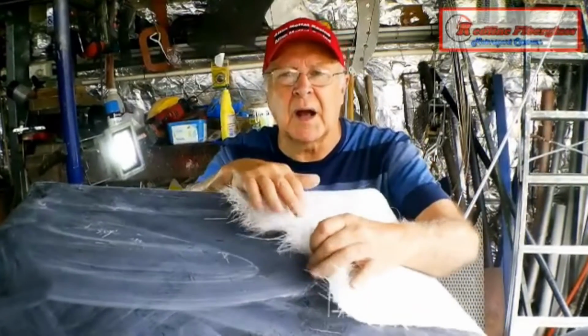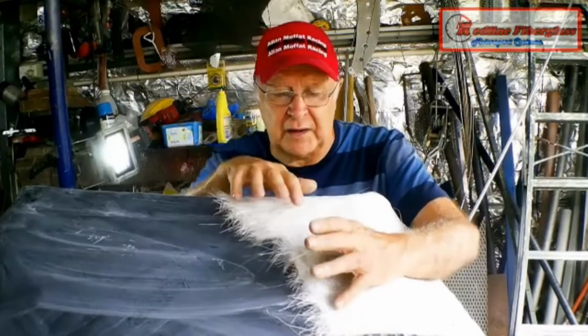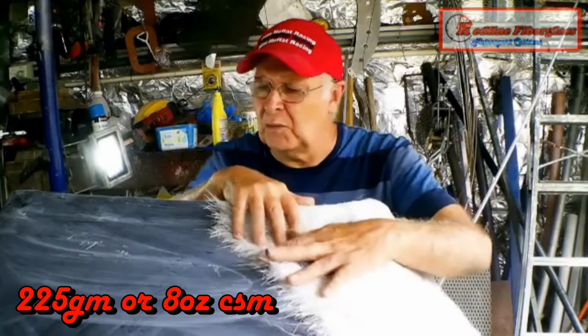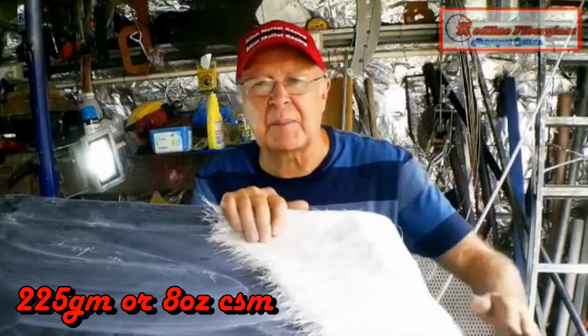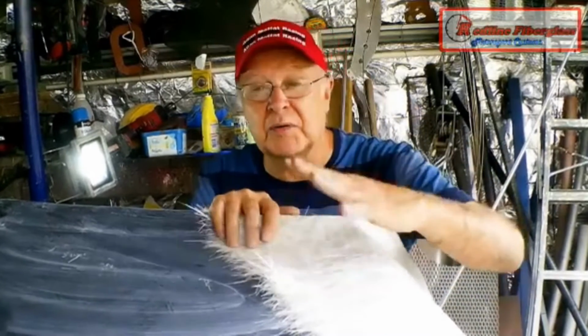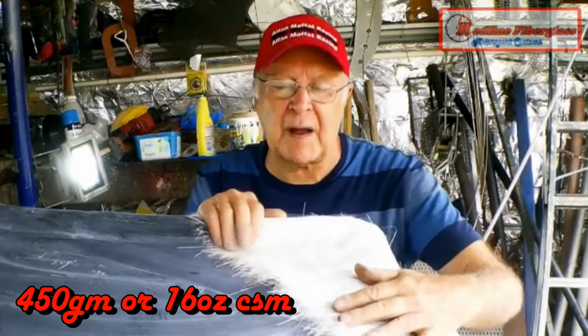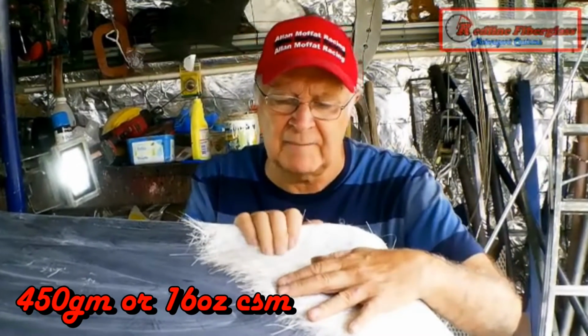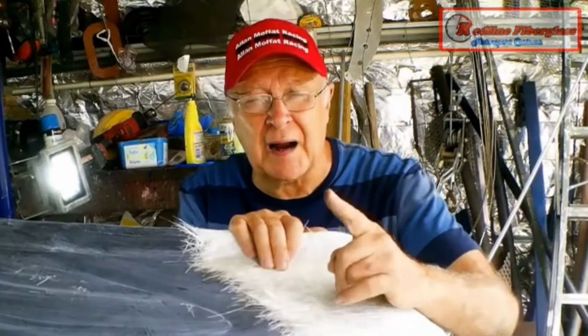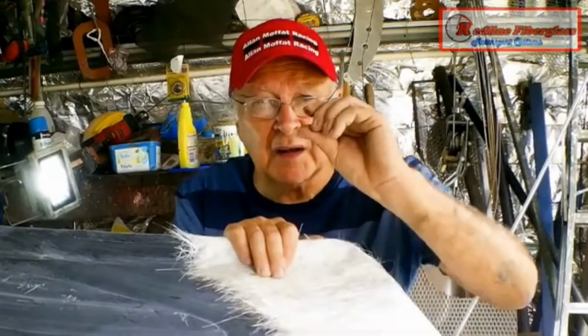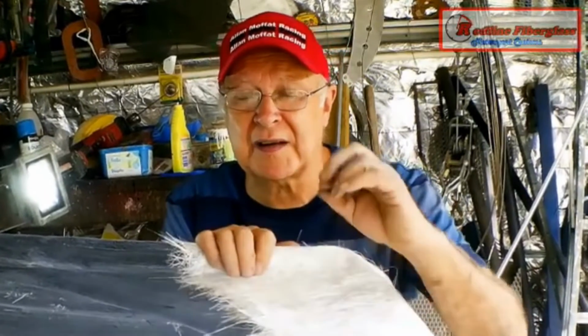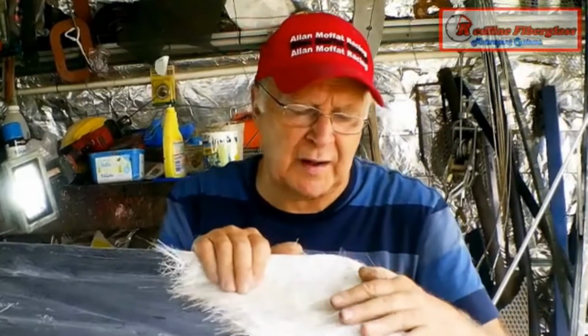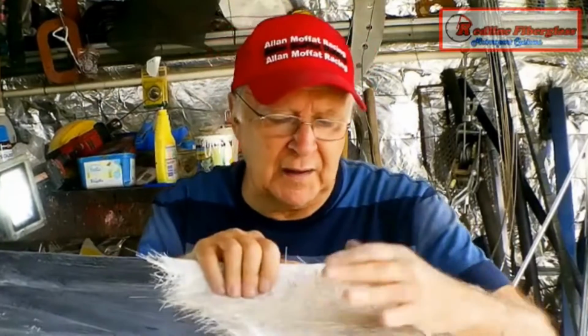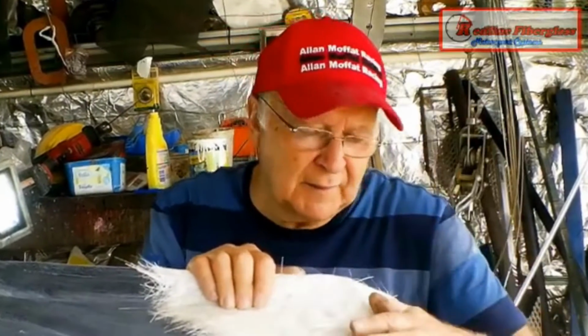There's two grades of it. I always start my jobs with a layer of the light 225 grams, which is fairly thin, but it takes up all the shape of your job really well. And then I'll put on two layers of this stuff, which is 450 chop strand mat, or CSM as it's called in the industry, and that gives you the strength that you need. With one layer of 225, two layers of 450, you get a 3mm thickness. And in most car racing rules, that's the thinnest that you can make it, but it gives you a panel that's strong enough. So throw away your woven cloth and get chop strand mat. Trust me, you'll love it once you start using it. It just breaks up and conforms to the shape of the tightest, curviest job.